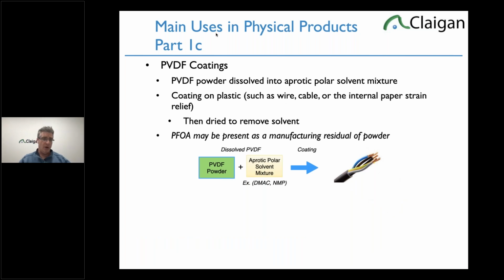Where we see fluoropolymers in electronics almost the most is as a coating. And this is PVDF. It's polyvinylidene fluoride. It's not PTFE, which is polytetrafluoroethylene. It's a very slightly different polymer. And so what you do is you make PVDF powder, which is very similar to PTFE powder. You put it into a polar solvent. Think of it as acetone. They're not. They're higher end. They're DMAC or NMP. They're almost always SVHCs. They put it in a solvent. They paint it on. Solvent dries. You're left over with PVDF.